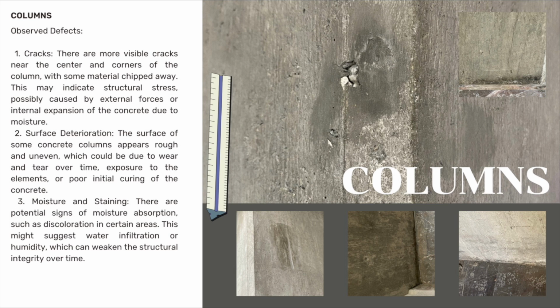In surface deterioration, the surface of some concrete columns appears rough and uneven, which could be due to wear and tear over time, exposure to elements, or poor initial curing of concrete. In moisture and staining, there are potential signs of moisture absorption in some columns as well, especially on the ones in the exterior areas of the basement floor. And these signs of moisture absorption, such as discoloration in certain areas, are also shown in these columns. This might suggest water infiltration or humidity, which can weaken the structural integrity over time.